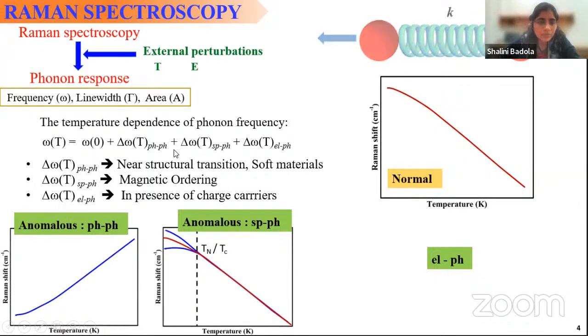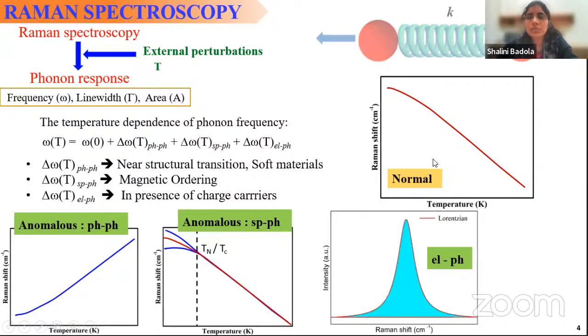So if we consider temperature as the external perturbation, the temperature dependence of the phonon frequency is generally given by this equation, which carries the contribution from phonon-phonon, spin-phonon, and electron-phonon terms. When the contributions from these terms are negligible or small, the temperature dependence of the phonon follows the behavior represented by this schematic. That is, as temperature increases, the phonon frequency should decrease. This behavior is known as normal behavior, and deviation from this behavior is termed anomalous.